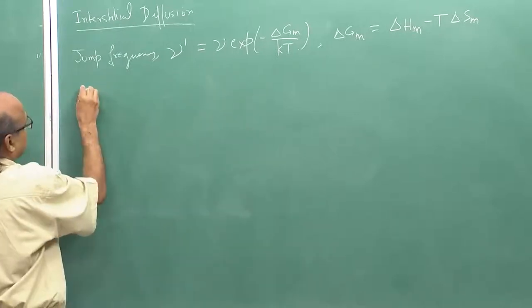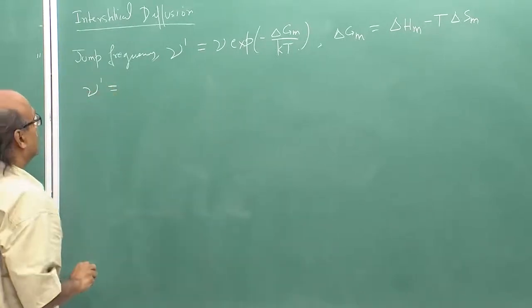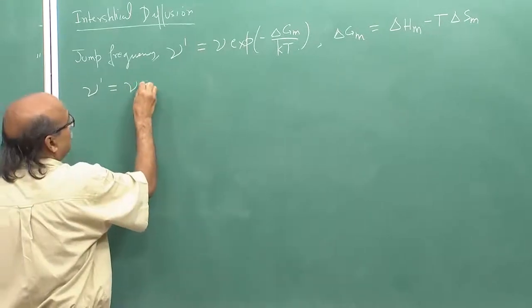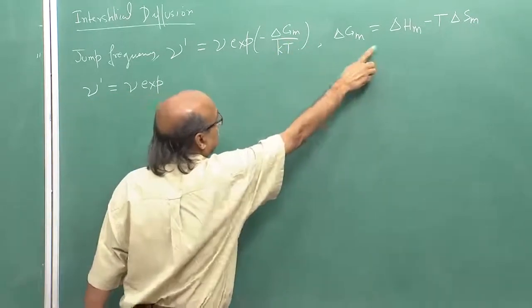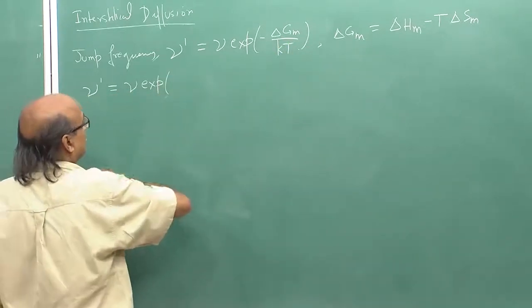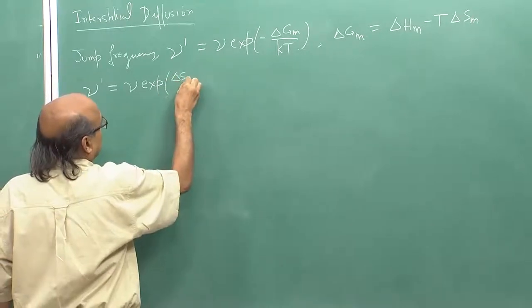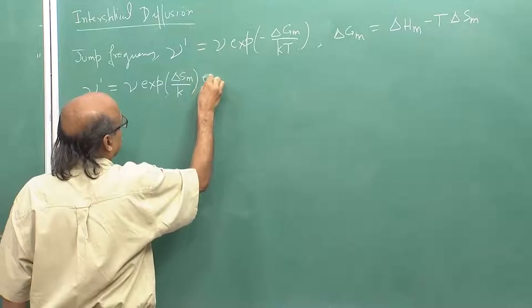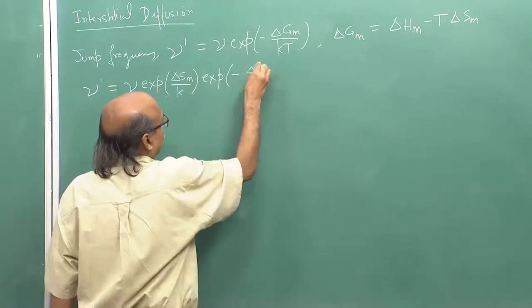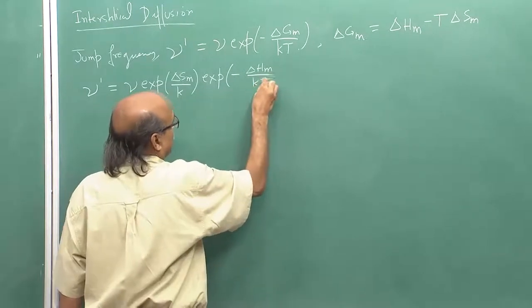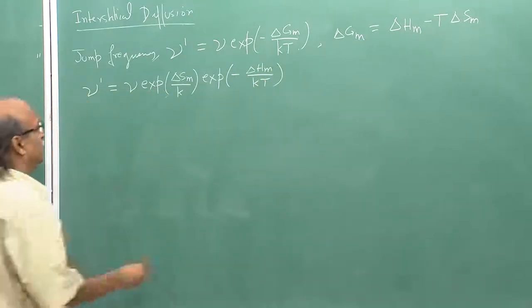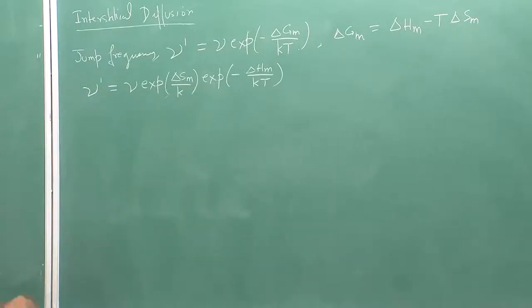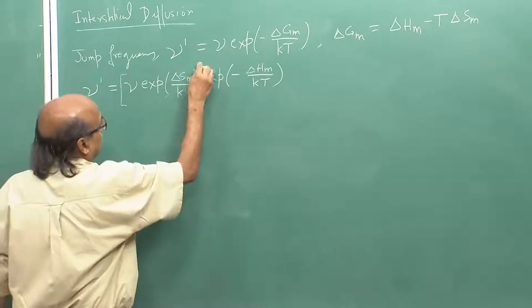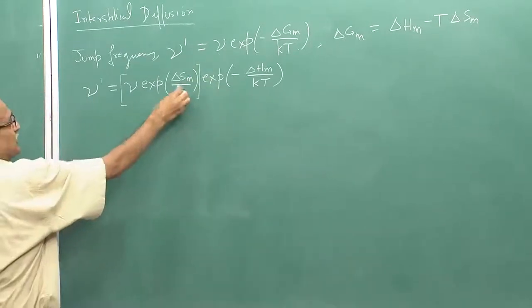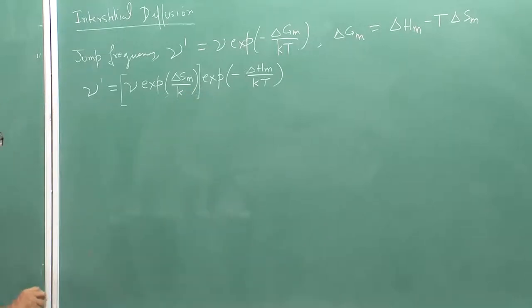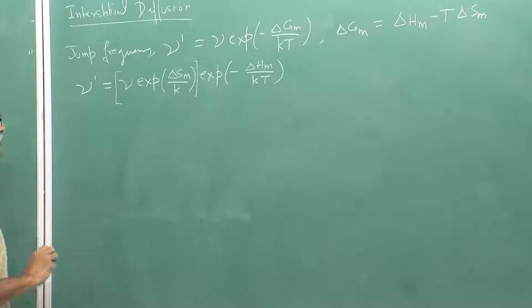So, substituting this, the jump frequency for interstitial diffusion is given by nu exponential, substituting for delta Gm, exponential delta Sm upon k times exponential minus delta Hm divided by kT. If we can assume delta Sm to be independent of temperature, then I have the pre-exponential term nu exponential delta Sm upon k to be independent of temperature, while the exponential term is dependent on temperature.